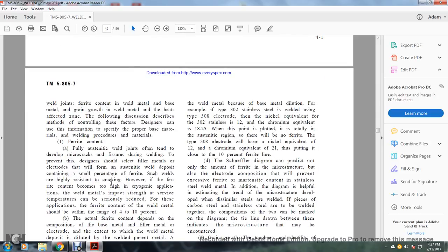1. Ferrite content. Fully austenitic welded joints often tend to develop microcracks or fissures during welding. To prevent this, the designer should select filler metal or electrodes that will form austenitic weld deposits containing a small percentage of ferrite. Such welds are highly resistant to cracking. However, if the ferrite content becomes too high in cryogenic applications, the weld metal's impact strength at low temperatures can be seriously reduced. For these applications, the ferrite content